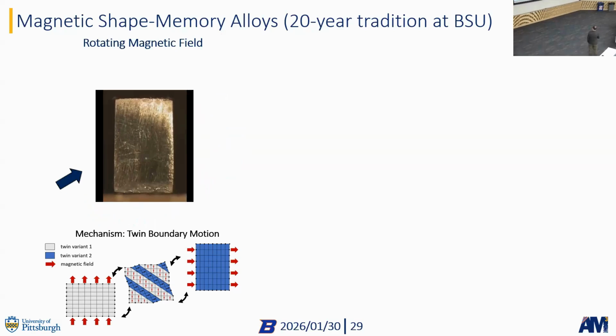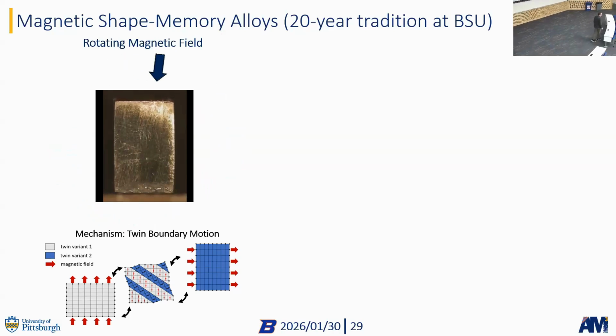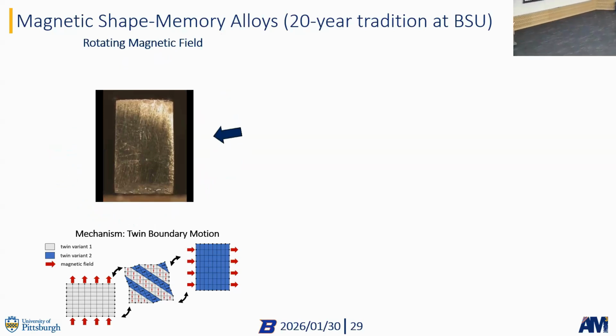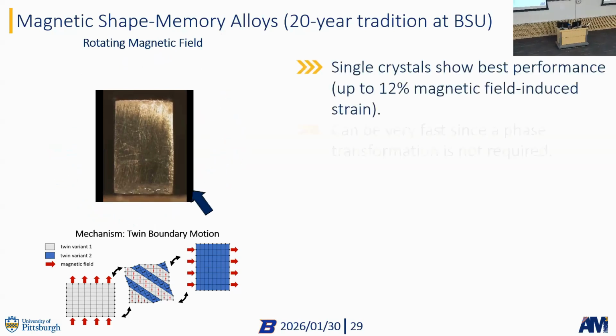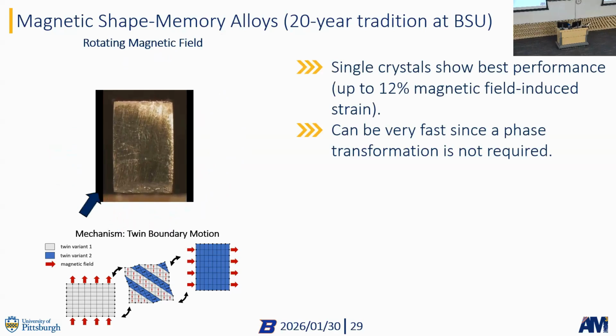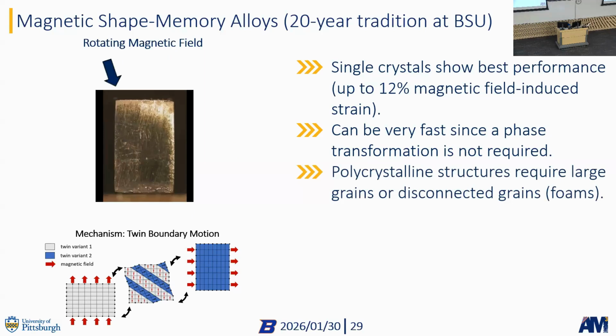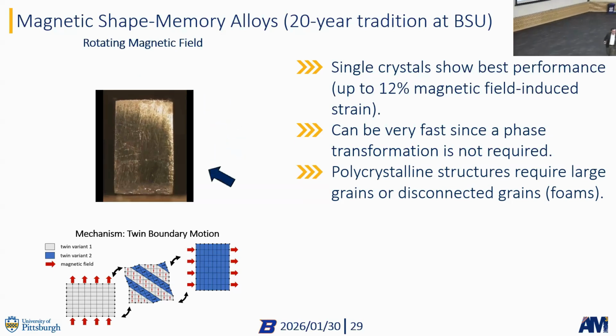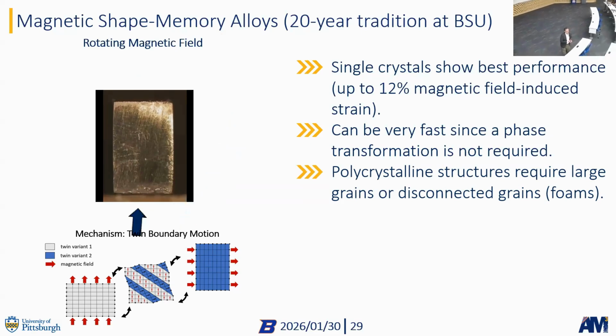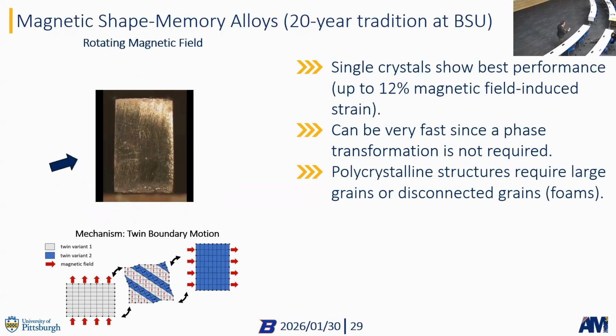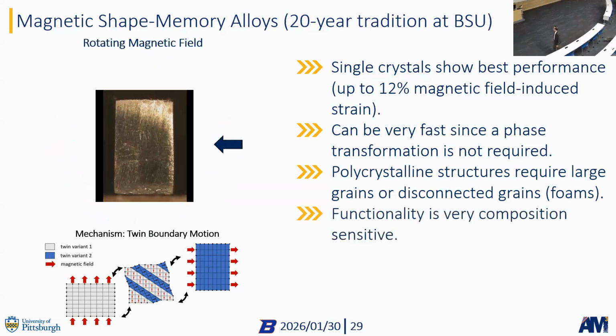As a quick introduction, magnetic shape memory alloys are actually really cool materials. They're solid and they deform up to 12% in a single crystalline state when you apply a magnetic field or change that magnetic field, right? What is really cool about them is that they perform really fast because they don't need a phase transformation. You don't need to heat and cool them, right? Like shape memory alloys. As polycrystalline materials, they're terrible, right? If you just cast a nickel manganese gallium magnetic shape memory alloy, they will probably not do anything. So you either need very large grains compared to the size of your part, or you need to add porosity and disconnect those grains, right? So that each grain can act as a single crystal by itself.